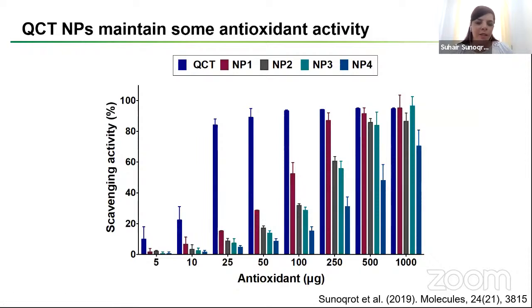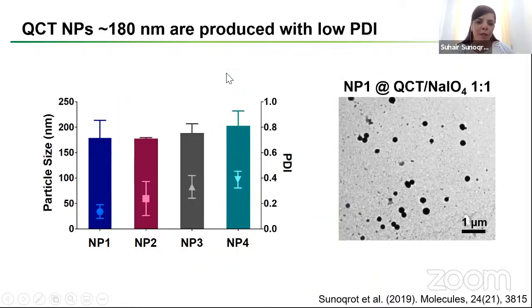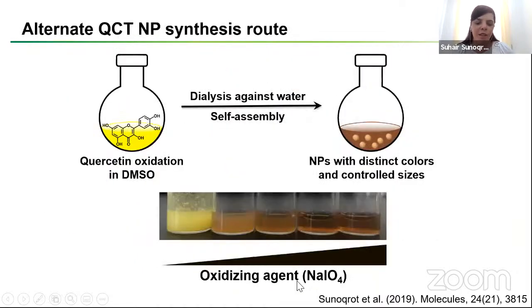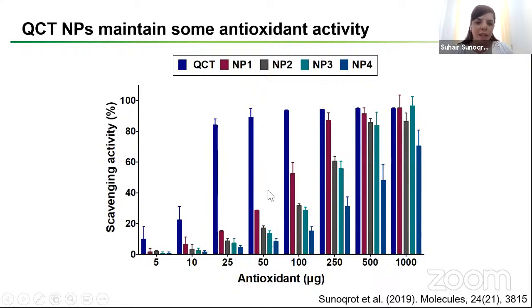And we tested their antioxidant activity. The highest in the navy bars belongs to the unmodified quercetin. As you know, it's a very potent antioxidant. And after we make the nanoparticles, because we incubate with an oxidizing agent, we expect the antioxidant activity to be reduced. And it was lower, but it was still there. So they still contain some antioxidant activity.